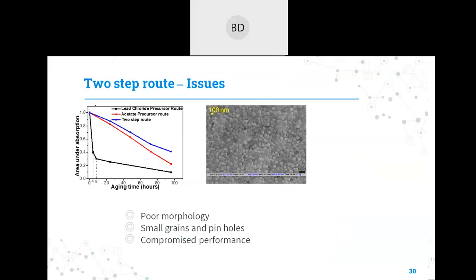So out of these results, we understood that the two-step route is degrading very slowly, but there have been some issues with the two-step process as well. It doesn't have that high a performance because of its poor morphology. The perovskite here is of poor morphology. You see here the grain size is very small, and you can see some pinholes also. So all these morphologies, small grains, pinholes and incomplete coverage in the perovskite film, compromise the performance. To have a better performing perovskite, all you need is a perovskite film with a very large grain size and very high quality grains. The better the coverage, the better the grain size, the better the crystallization or the compact nature of the perovskite, the higher the performance.